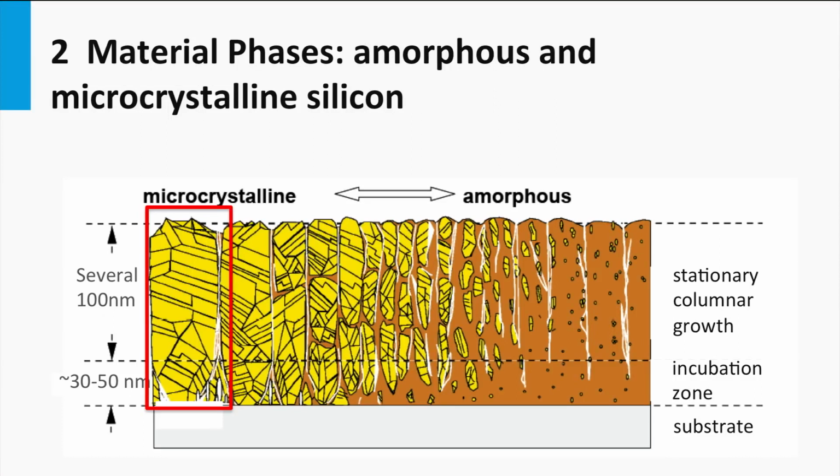Going from right to left, the amorphous phase is changing into a mixed phase with a few small crystalline grains, to a phase which is dominated by large crystalline grains and a small fraction of amorphous tissue. The best nanocrystalline silicon bulk material used in solar cells has a network close to the so-called amorphous to nanocrystalline silicon transition, and its crystalline volume fraction is in the order of 60%.